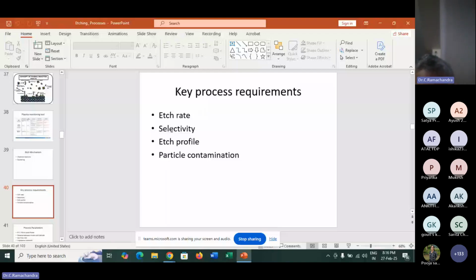Selectivity is very important. I'm etching silicon, but I don't want to etch aluminum, or I'm etching aluminum, I don't want to etch silicon dioxide. So we need a selectivity generally more than 100 in industry. Etch profile: in some applications isotropic is okay, in some applications directional etch is okay, and in some I need a vertical profile. That is quite challenging. And particle contamination should be limited. Otherwise, ultimately, it degrades the device performance.